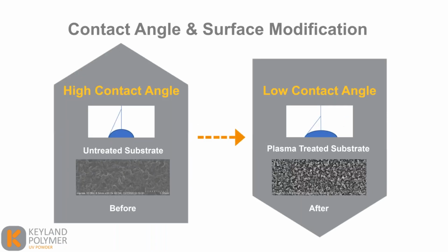So we can't see this optically, this change that occurs before and after plasma treating of a material, but it can be measured. Typically, it's measured with dyne testing. And what you see on the left is a high contact angle. So this is a pre-plasma treated part. And then on the right is the contact angle changing, so an after plasma treated part.